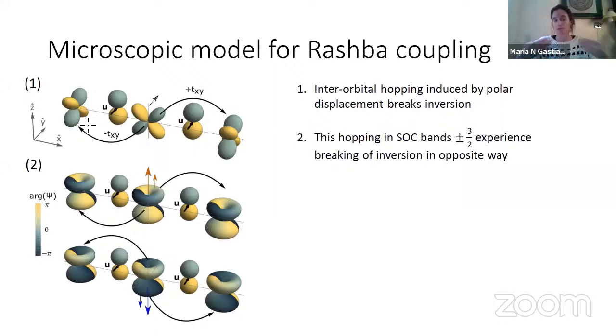Now, it's nice to see that you can get this kind of hopping, but I just told you that a good description of the conduction electrons is given by the spin orbit coupled bands. So I'm going to map this process that breaks inversion to the plus and minus, the spin up and down, so this plus minus 3/2 that I mentioned before. If you do that mapping, you see that the inversion symmetry, the fact that the hopping changes sign to the right and to the left, is still inherited, still present. But the main extra ingredient you obtain is that the sign changes in exactly the opposite way. A pseudospin up band will hop into another pseudospin up band to the right, say with plus t, and the pseudospin down band will do it with a minus t.